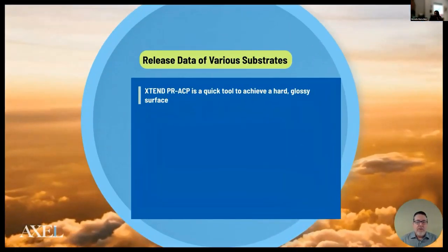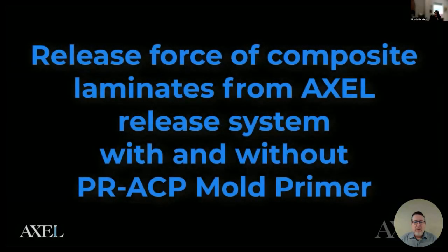Moving on to some of the testing we've done, and we've done a lot more testing than you'll see in this webinar, for most thermoset resin systems: demolding, making molds off of patterns and various substrates, as well as molding parts, everything from hand layup with simple e-glass to carbon reinforcements with higher temp advanced composites resins such as epoxies and cyanate esters. So in the first case, we sealed HDF, high density fiberboard, with 5 coats on one half and no primer on the other half.